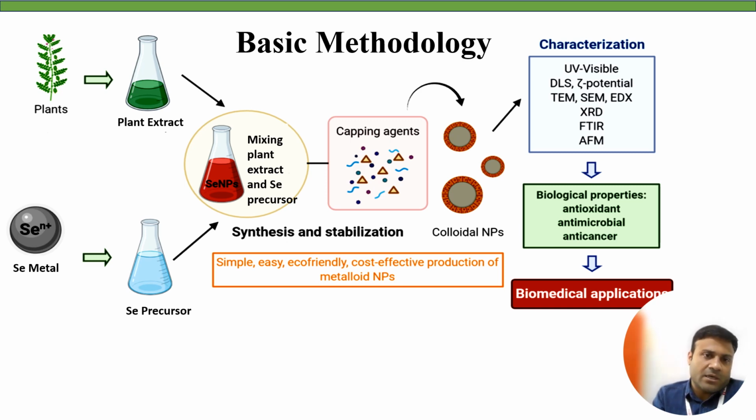Following synthesis, the nanoparticles were further characterized by UV-visible spectroscopy, transmission electron microscopy, and dynamic light scattering. The nanoparticles were also analyzed using FTIR to confirm the presence of functional groups from the plant extract on their surface. After purification to remove excess reactant or byproduct, selenium nanoparticles were stored in a suitable solvent in a cool, dark place to prevent aggregation or degradation.